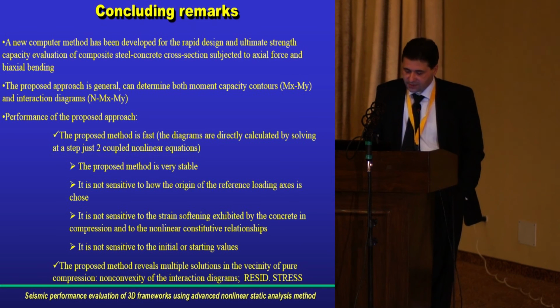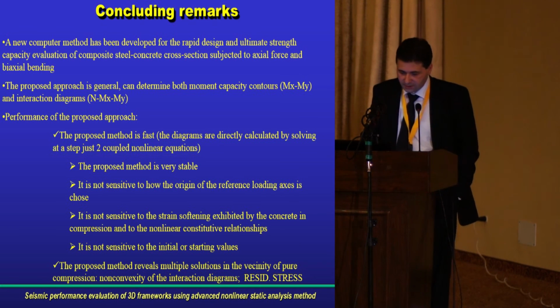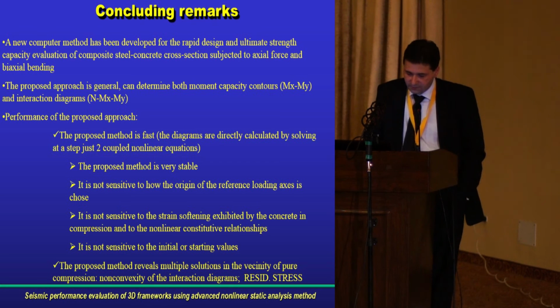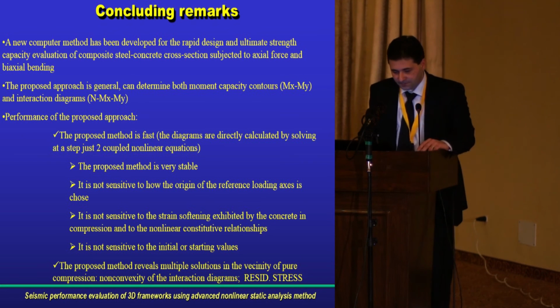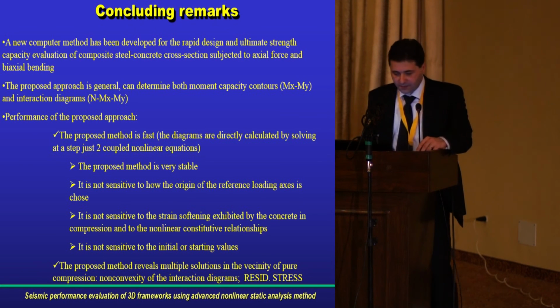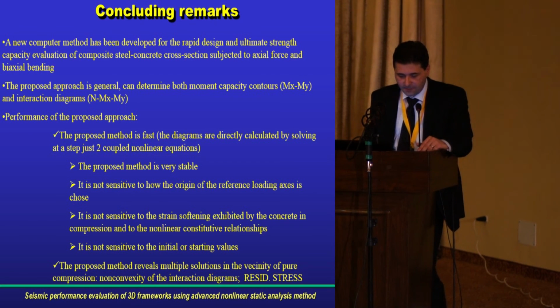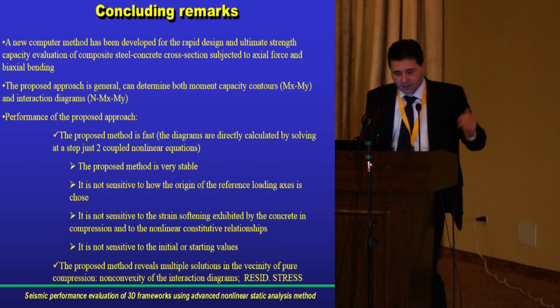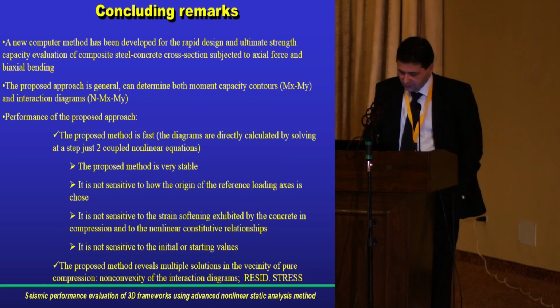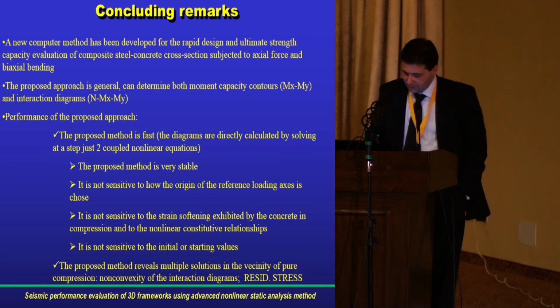The proposed method is very stable. The method is not sensitive to how the origin of the reference loading axis is chosen. It is not sensitive to the strain softening exhibited by the concrete in compression and to the nonlinear constitutive relationships. It is not sensitive to the initial or starting values. And very important, the proposed method reveals multiple solutions in the vicinity of pure compression. The interaction diagrams are non-convex. And also, we highlighted that the residual stresses play an important role when the compressive axial force is high.